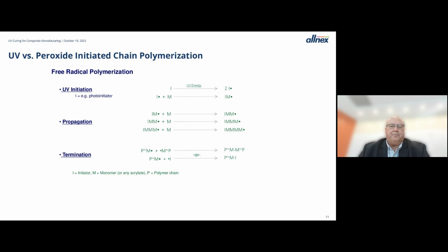So if you're familiar with thermally initiated free radical polymerization, it's not that big a step to move to UV initiated free radical polymerization. The other thing to note is that in the termination step, there are two radicals necessary for termination, while there's only one radical necessary for propagation. That means as you increase the radical concentration, you increase termination rate.